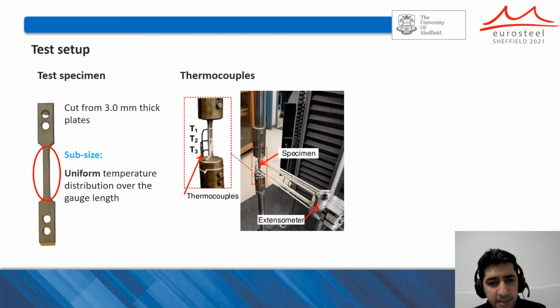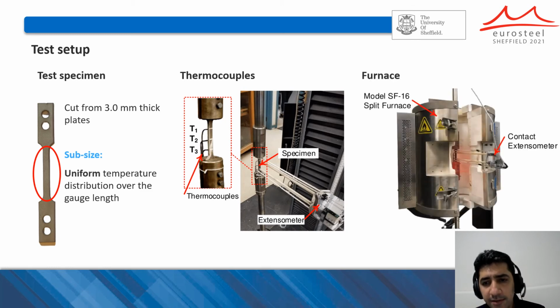You can see 3 thermocouples attached to the gauge length of the sample, and the thermocouples are directly connected to the furnace controller, so that the temperature of the sample is directly controlled. The specimen is mounted on the loading machine, and you can see the extensometer, which is attached to the sample to measure the strain. And here is the split furnace, which is used to apply heat to the sample.